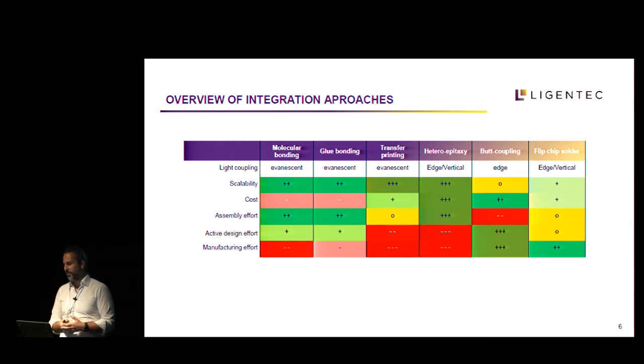The last approach is flip chip solder. And here you use solder bumps or solder stripes, and this electrical layer helps you with the alignment of the chip, because the surface tension of the solder will auto-align your chip to whatever lithographic layers you have aligned your metal layer. And you can make it either edge or vertical.